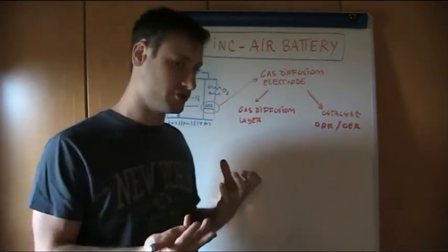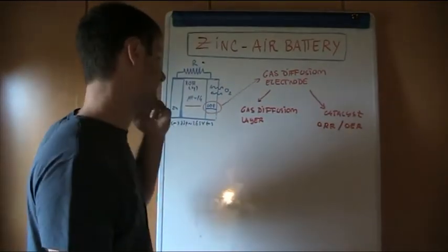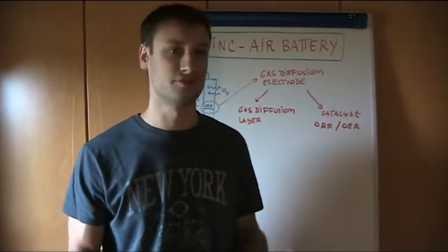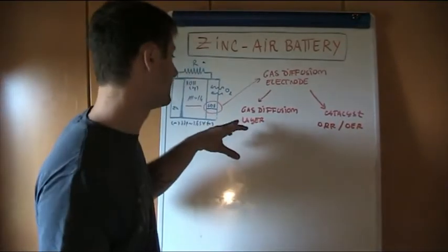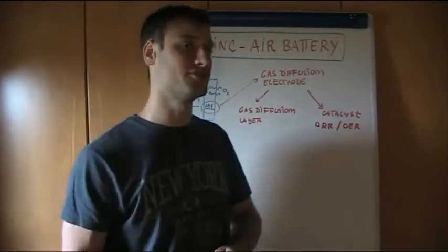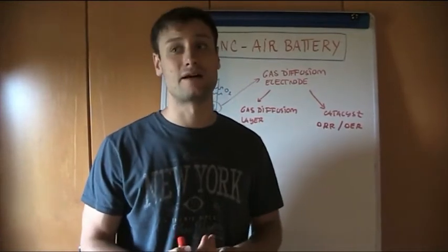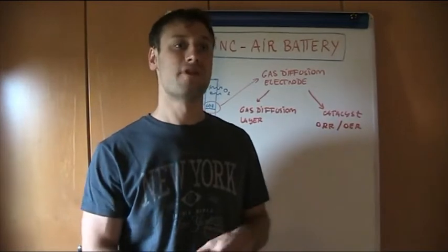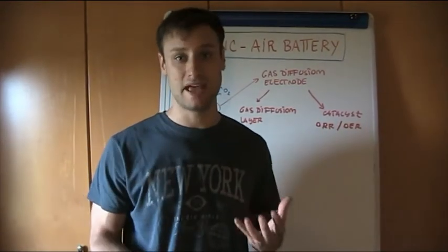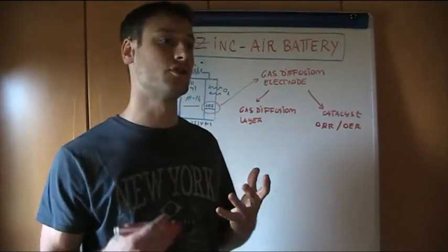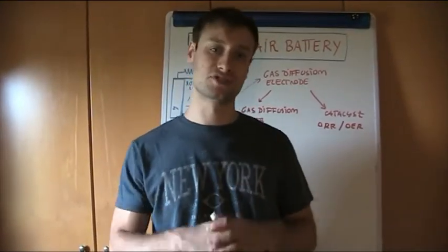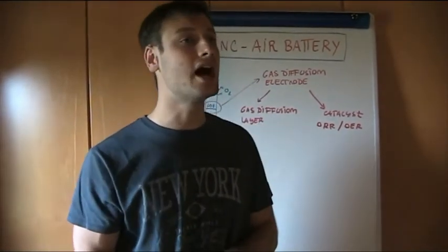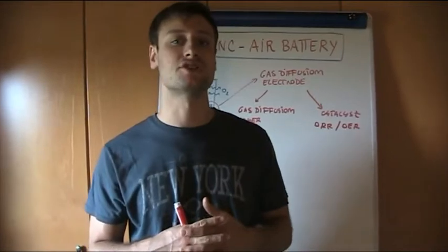And from a practical point of view, we can say that the gas diffusion layer is a carbonaceous material. It's a carbon material in order to ensure a certain conductivity. And basically it is often composed of a weave of carbon fibers in a specific carbon cloth, or could even be created from pressed carbon fibers in a carbon paper. And obviously it is created in order to ensure a microporous aspect. It seems to be smooth, but with a huge surface area in order to maximize the diffusion and also the interactions with the electrolyte.